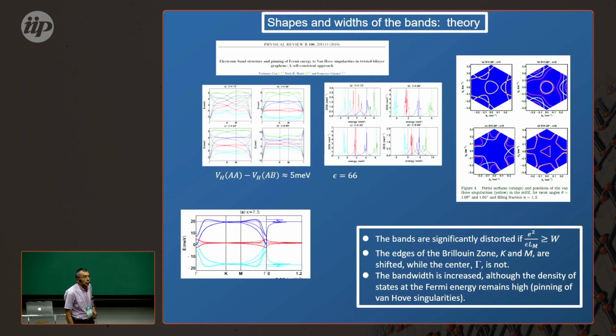In addition, it was already noticed way back by Rafi Bistritzer and Alan MacDonald, not only that there were flat bands in these systems, but that the charge induced when you break charge neutrality by applying a gate and doping the system was highly inhomogeneous. So in addition to an average charge induced by applying a voltage, there was also a charge density wave with the periodicity of the moire, which was very significant.